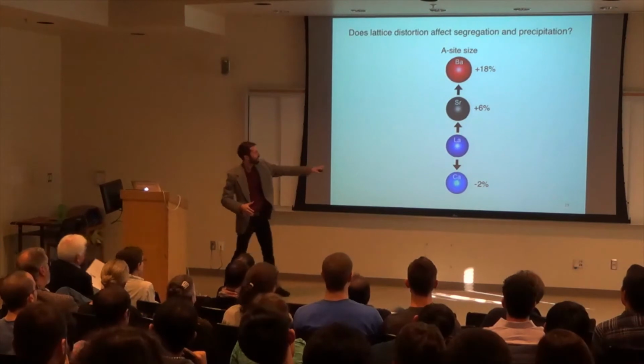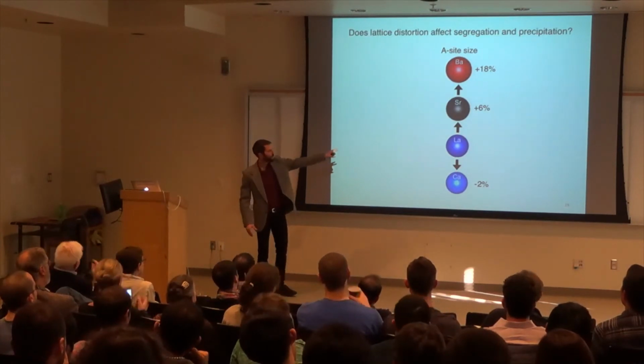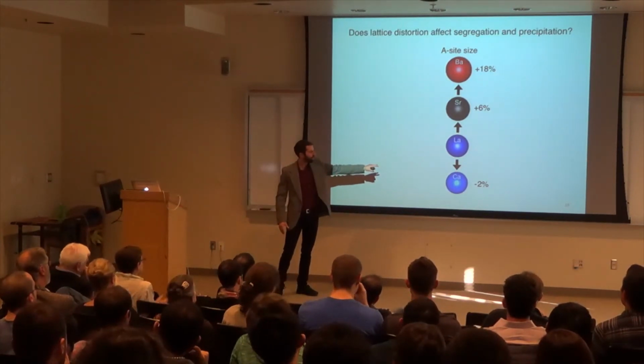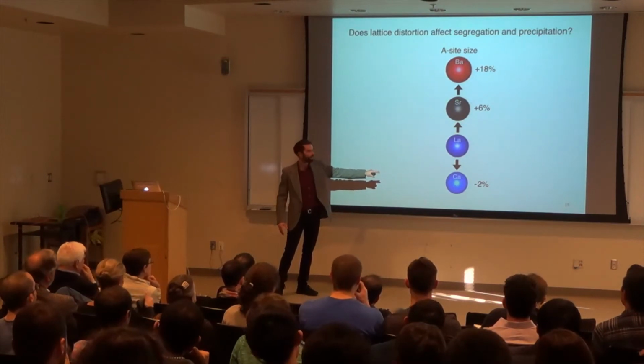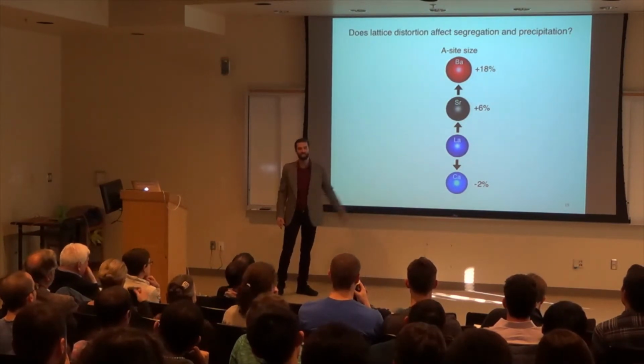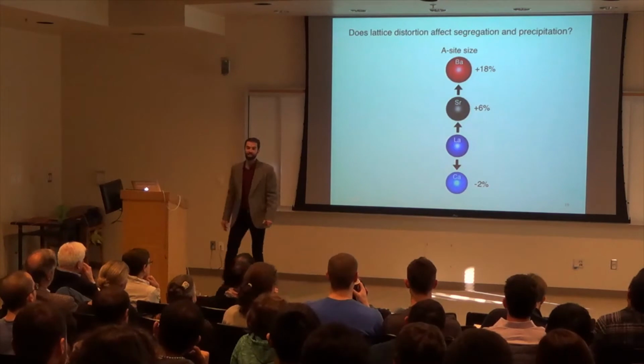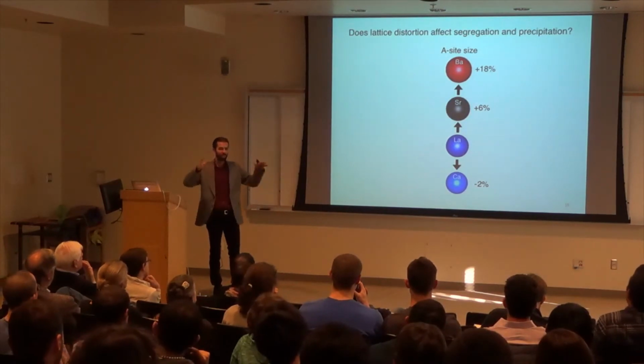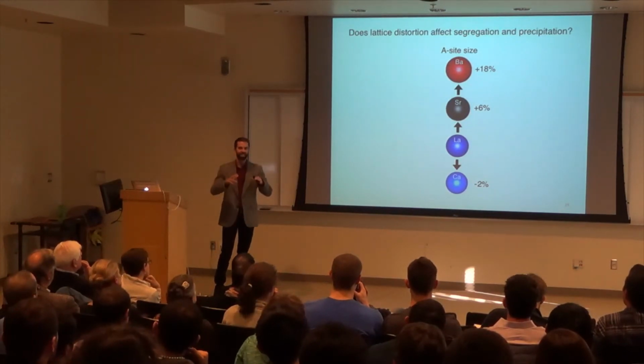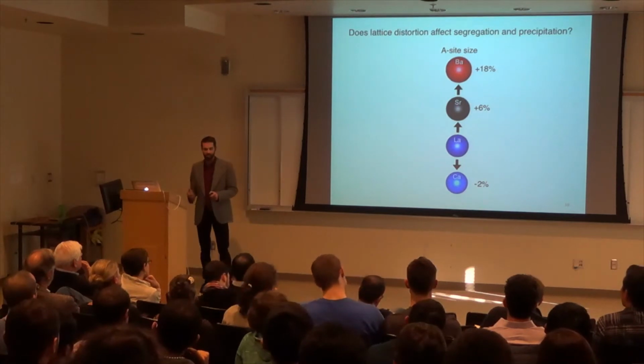So what we see here is the ionic difference between the lanthanum and the calcium. The size of it is about 2% smaller. And then when you go up to barium, that's 18% larger than that of lanthanum. So you can imagine the barium doesn't fit so well in the lattice. So let's see what effect that will have.